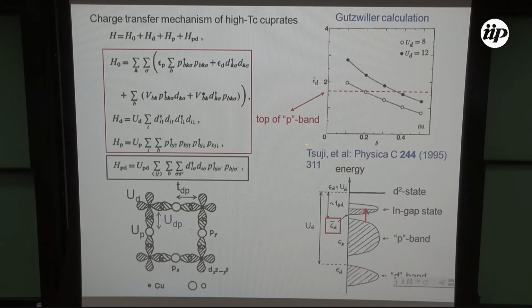Actually, this is a very old calculation, but on the basis of the 3-band dp model, and using the Gutzwiller calculations, we obtain the bottom of the in-gap state, Ed tilde. So depending on the size of Ud, this Ed tilde decreases as the doping is increased.